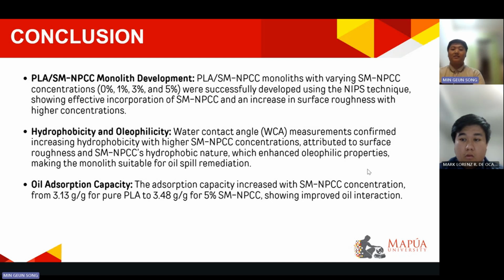The adsorption capacity increased with SM-NPCC concentrations from 3.13 grams per gram for pure PLA to 3.48 grams per gram for 5% SM-NPCC, showing improved oil interaction.